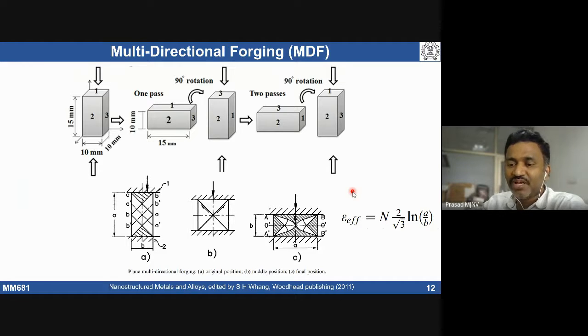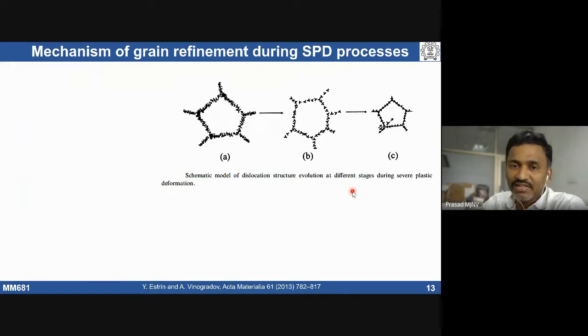If I talk about the mechanism of how the grain size is refining, the easiest explanation people have given is that when you deform material to very large strains, a cell structure develops. A lot of dislocations are generated and rearranged in the form of a cell structure in the deformed material. When you deform more and more, you may see some kind of dynamic recovery even at low temperatures. Opposite sign dislocations annihilate each other and can form subgrains, and these subgrains can become high angle grain boundary grains with more and more dislocations entering the material.